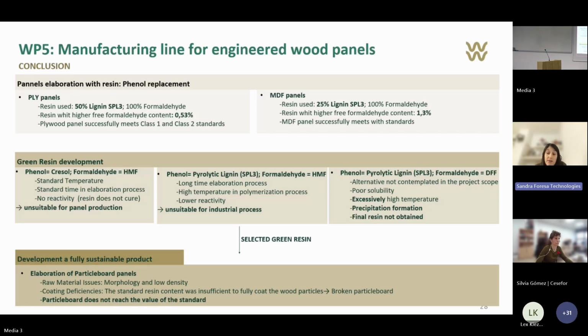The issue is that this resin is not 100% bio-based, and the free formaldehyde content obtained is too high. Therefore, the goal was to elaborate a 100% bio-based resin.